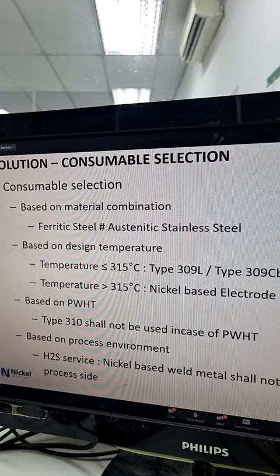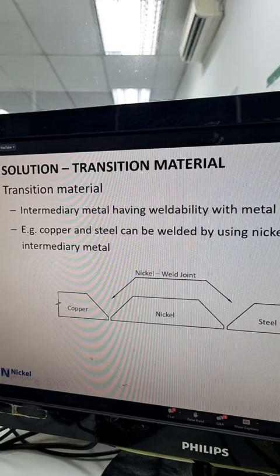And nickel is not the solution to everything, because you cannot use nickel in hydrogen service or H2S service. Nickel has enormous advantages in the case of a dissimilar joint, but there are certain cautions, or precautions rather, that also need to be addressed while you decide or plan to use nickel for a dissimilar joint. There is also the possibility to add a transition material similar to the steam generator. Suppose you have to join copper to steel, again you can think of nickel being added.